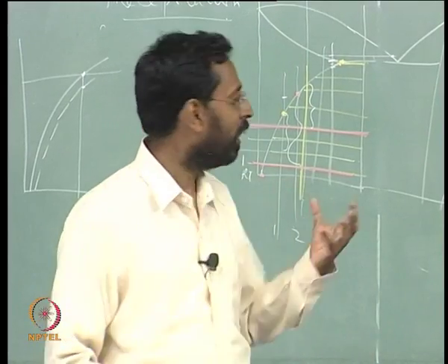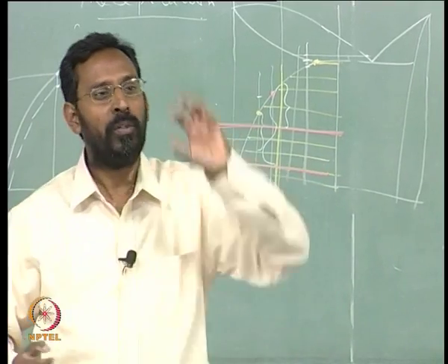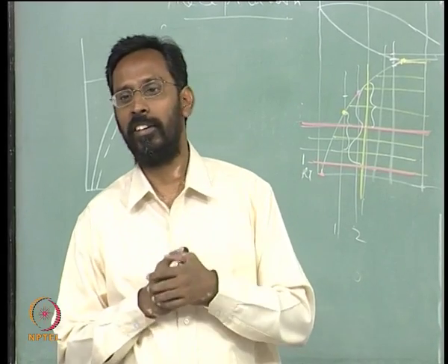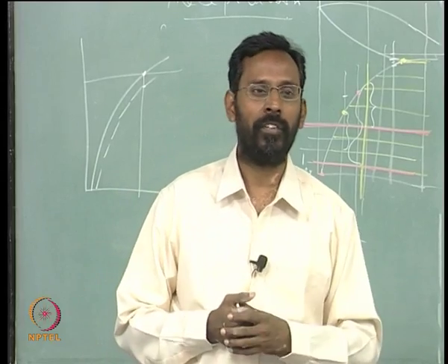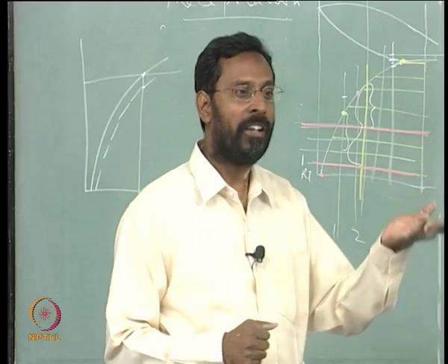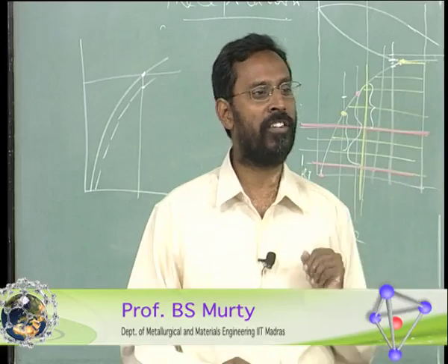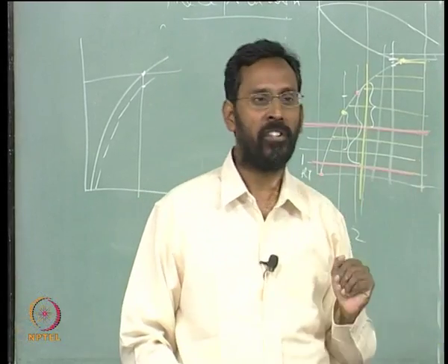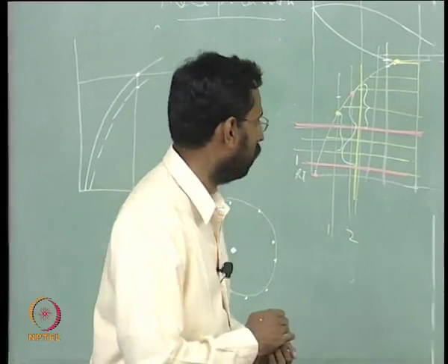So, if you take such a quasicrystalline unit cell and keep joining them, you will always have some voids left out, which we call a frustration in crystallography. So you will always have such voids left out, and that is why people say these phases are at a high energy state because of those voids that are available, and that is why they are more metastable when compared to the stable structures. Okay, we will stop now.